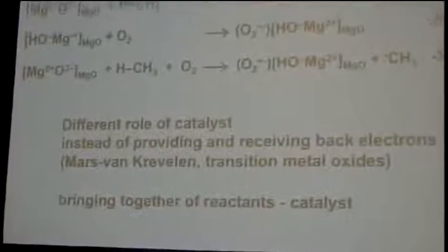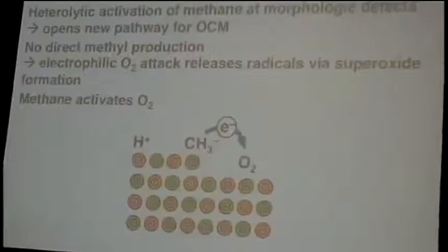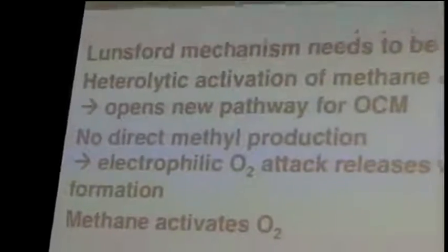So what did we learn? We see a completely different role for the catalyst as opposed to redox catalysts with transition metal, with redox active catalysts. The catalyst is really only providing the surface on which both reactants, methane and oxygen, are exchanging the electron.